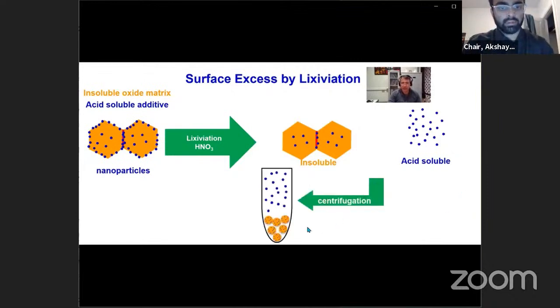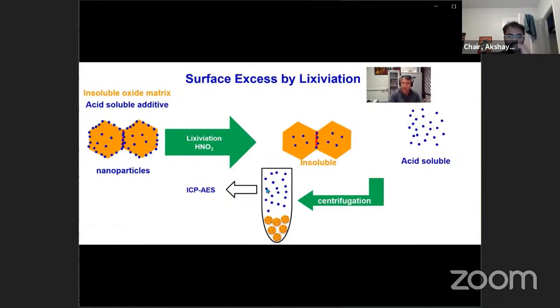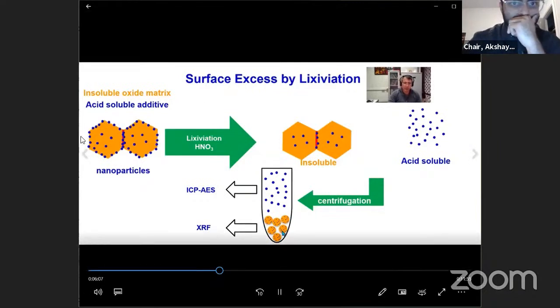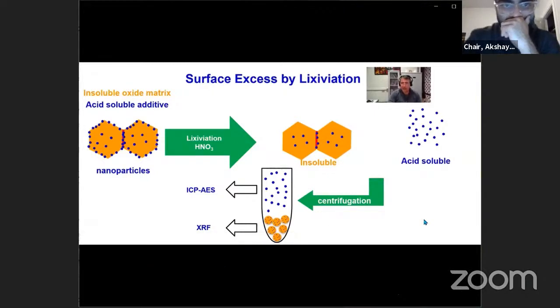Then by centrifugation, we have a separation of phases. Here it's possible to know the concentration of atoms in the solution by ICP, for example. And here it's possible to know the concentration of additive in the nanoparticles in the insoluble part. By this method, it's very easy to know the concentration of additive in the surface and the surface excess.